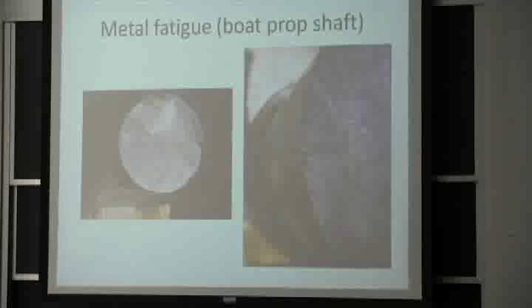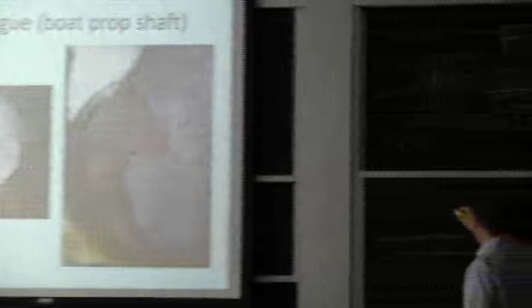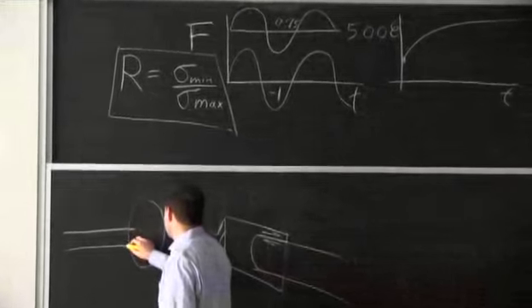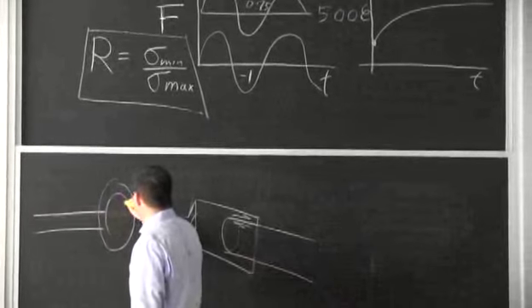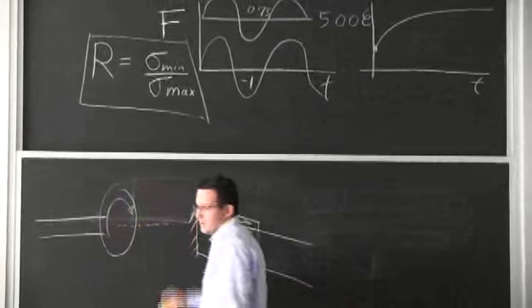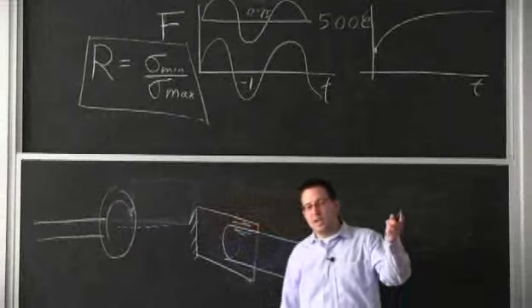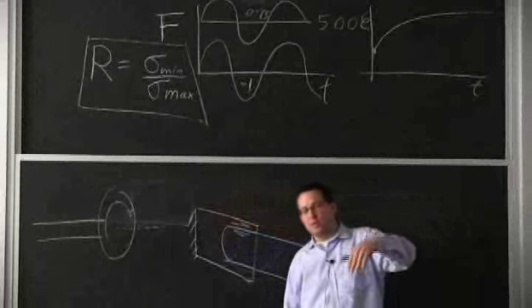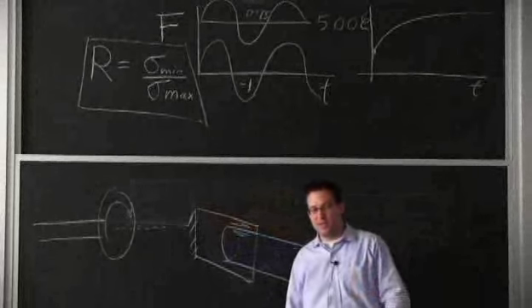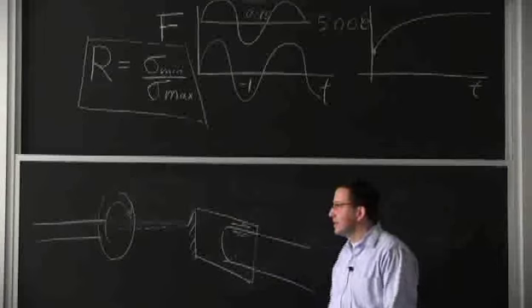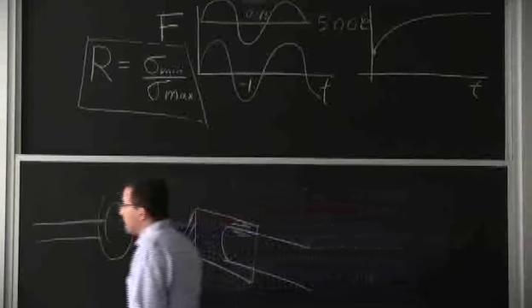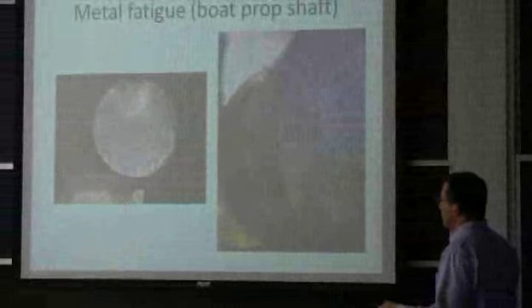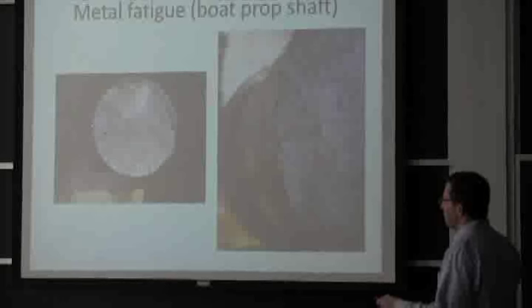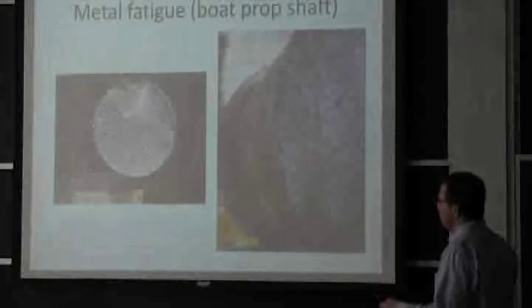So what you have is as simple as this. The shaft goes off the back, and you have the prop. I'm going to make it circular. And it's rotating, but the water level is right about here. And therefore, at each turn, you get a huge bending load in the shaft. And that's what I saw on the fracture here, because what I see is the crack started in the lower left corner right here, and you see all these lines over here up until this point.